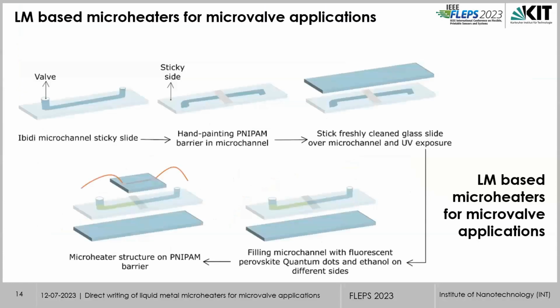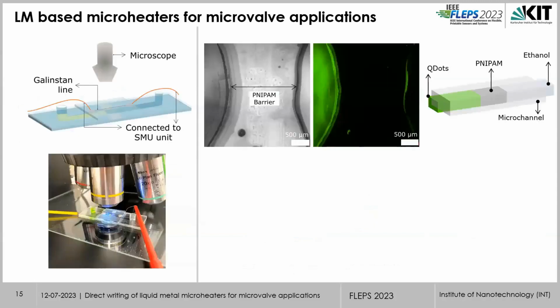Then we use these microheater structures for microvalve applications, let's say, for controlled mixing of two solvents or two materials. Here we first have this microchannel sticky chip, with a microchannel on one side. We block this microchannel with PNIPAM, a hydrogel that has a critical temperature around 32 degrees, going from hydrated to non-hydrated state. Then we attach a glass slide at the back. Once one side is blocked, we fill it with perovskite quantum dots for fluorescent purposes under the microscope, and the other side with ethanol. We put a microheater structure on top, and everything is observed under a fluorescent microscope.